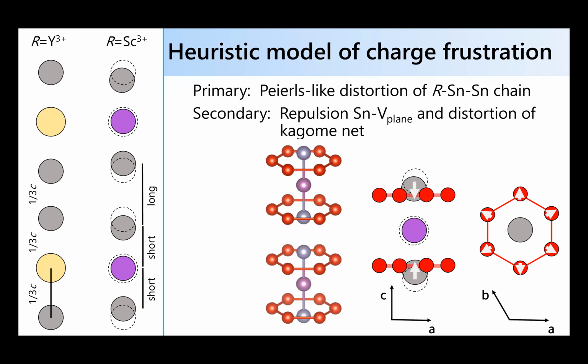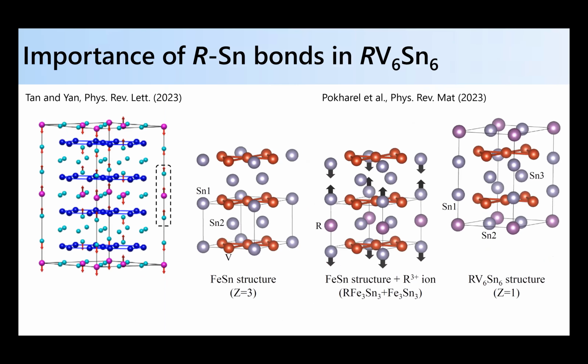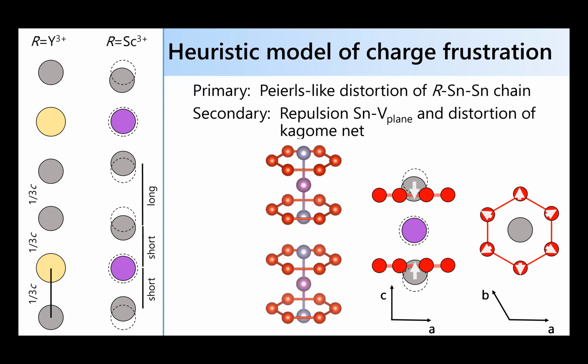And so one way of thinking about what the primary distortion mode is: if you think about the yttrium vanadium 6-tin-6 compound that I showed you originally, if you look along the c-axis, along what I'll call these scandium tin chains or yttrium tin chains, these chains thread through the honeycomb or the hexagons in the kagome network. All right. So in the yttrium system, the distance between tin and yttrium is about a third of the c-axis, and it's the same along the whole chain.